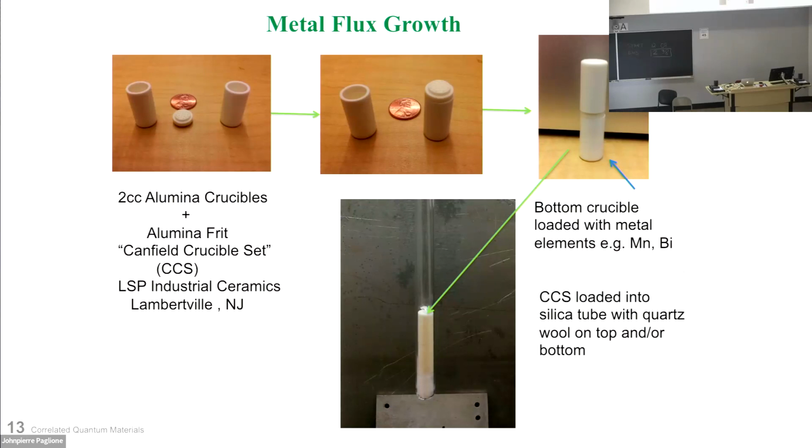And so when you put this in a centrifuge, the liquid goes through this ceramic piece, which has, you probably can't see it, a bunch of little holes in there which allow the liquid to easily go through it. And your crystals hopefully are too big to go through the holes too. So that's kind of what we're trying to do.